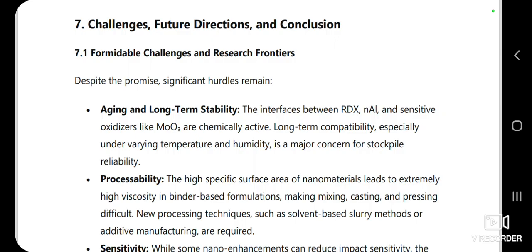Of course, we face real challenges in making these RDX nano-enhanced. The first one is aging and long-term stability. The significant hurdles are aging and long-term stability. The interfaces between RDX, nanoaluminum and sensitive oxidizers like molybdenum trioxide are chemically active. Long-term compatibility, especially under varying temperature and humidity, is a major concern for stockpile reliability.